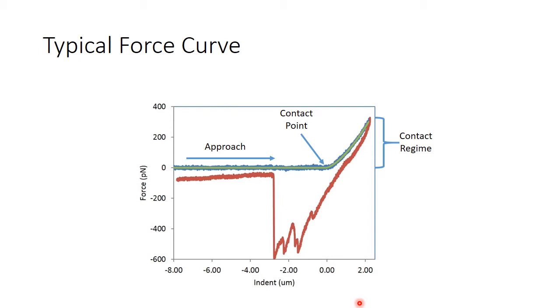We then pull the tip off of the sample in the retract portion, that's the red portion of the curve. And in this particular example, there is a very large adhesion between the tip and the sample. And so the tip is kind of stuck in the sample and releasing slowly bit by bit, and then finally it pops out or snaps out of contact before fully retracting. Typically, we are fitting the contact portion of the curve, and so the green line here is the fit to this data.